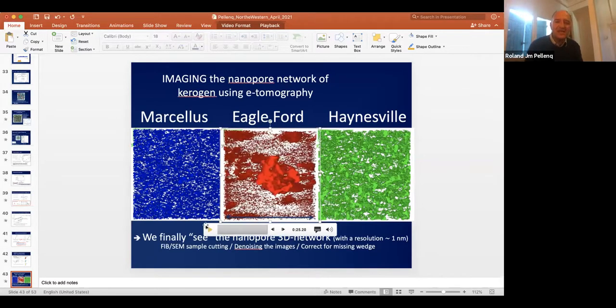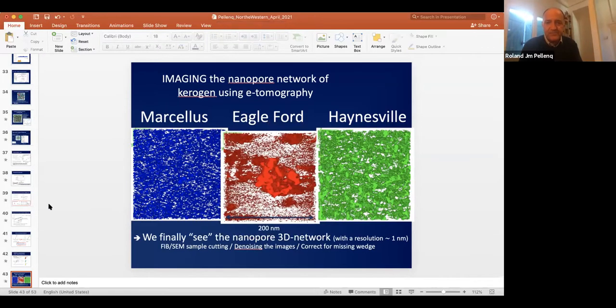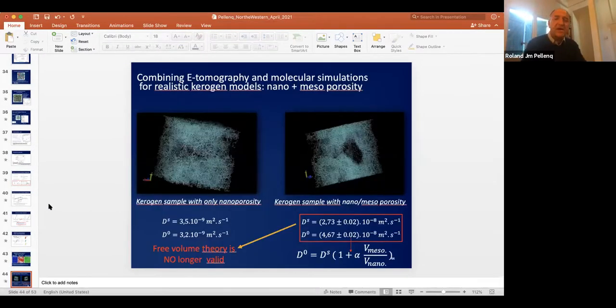So the story is the following: to make accurate predictions we obviously need to take into account those pores. This is what we did. We did a big simulation chunk of the nanoporous carbon called Kerogen, and we carved out, we dug into it the pores that we actually measured from the tomography experiment. We relaxed everything. So now we have a system that is actually realistic, in the sense that we have nanopores, sub-nanopores, and bigger pores. For instance, in this case, we have this big pore sitting in the middle of the sample.